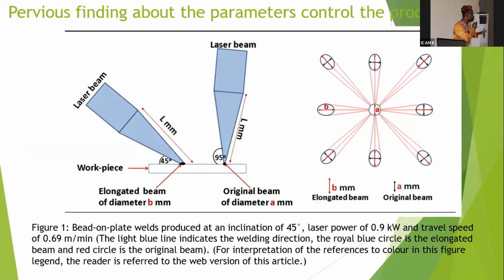Our previous experiments have shown that if you stand the laser directly on the surface of the powder, you get a perfect circle, the spot size. By the time the laser goes to an angle, we see that an elliptical shape at an angle of 45 degrees is formed. So A represents the original circle. You cannot work at 90 degrees directly because reflection will come back and destroy the laser. So in most cases, when you are using a laser, you have to tilt it in order to avoid being damaged. So the essence is that 5 degrees is removed from the 90 just to avoid this. Then we go to 45.